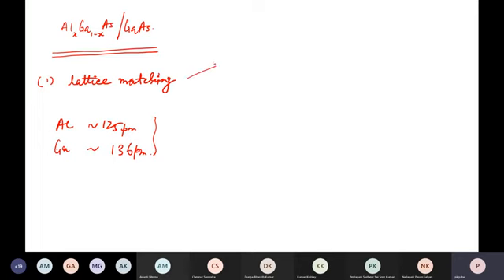Now regarding this lattice matching, I would like to point out aluminium arsenide has a lattice constant around 5.66 angstrom, whereas gallium arsenide has a lattice constant around 5.65 angstrom. So even if you change x from 0 to 1, x equal to 0 being the gallium arsenide material, and x equal to 1 meaning the entire gallium is replaced with aluminium, you are still meeting this lattice matching criteria. As I said, if you don't meet the lattice matching criteria, then there will be lots of defects in the interface, and that is not good for the mobility of the carrier.